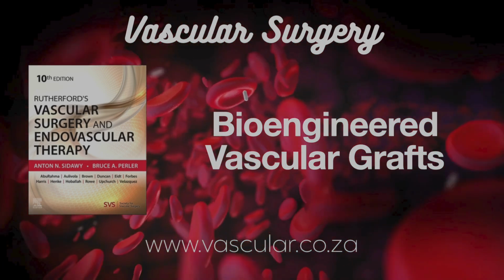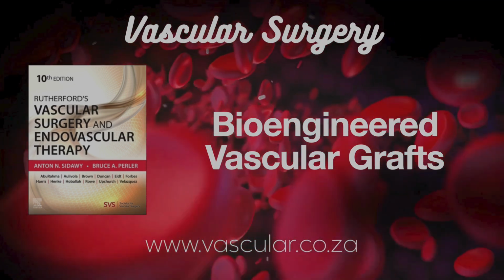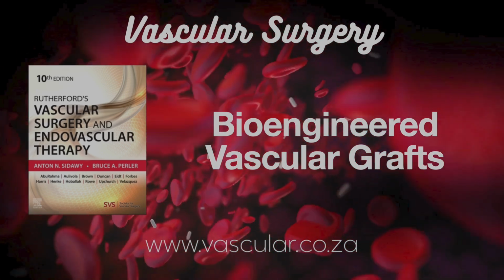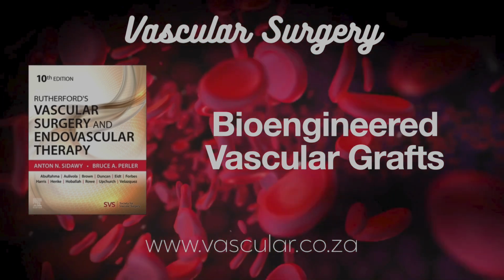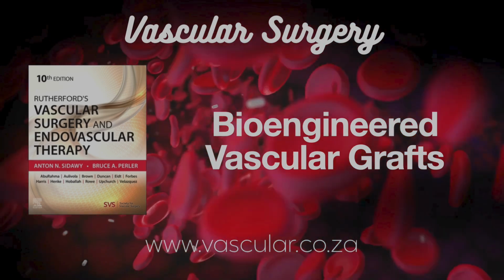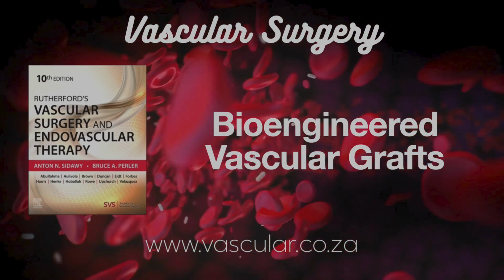Exactly. Yeah. Evidence of remodeling, development of an endothelial lining, and importantly, follow-up out to 5, even 6 years in. Some patients show no aneurysmal degeneration. It seems to hold its structure. That's key for long-term use. Absolutely. Phase 3 trials are ongoing now, directly comparing HAV to synthetic grafts and even fistulas for dialysis access. These could really change practice if the results hold up.